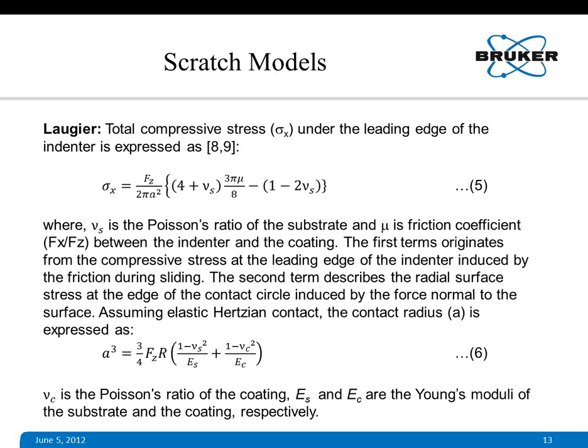Laugier considered compressive stress under the leading edge of the indenter and expressed the stress sigma x, that is tangential stress, based on two different parameters. One is with friction, that is mu, considering friction. Compressive stress at the leading edge of the indentation induced by the friction during sliding. Friction has a lot of influence on the scratch adhesion of any coating substrate. It has been found that if friction is high, it tends to show less scratch adhesion property of any coating